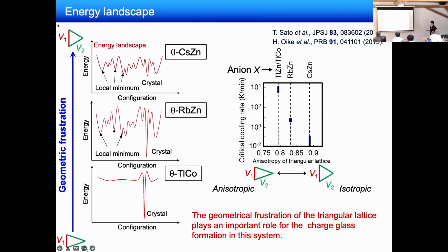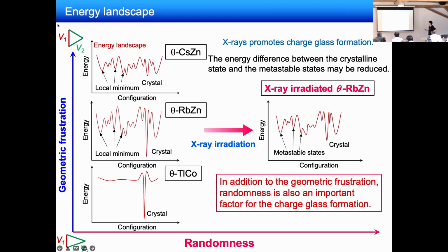Okay. So finally, I want to discuss the origin of this irradiation effect. As I've already discussed, the glass formation mechanism is dominated by the geometrical frustration of the triangular lattice. But in addition to this geometrical frustration, randomness is also a very important factor for charge glass formation in this type of compound. So this is my message.